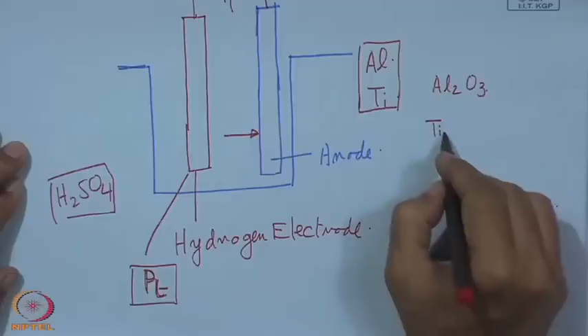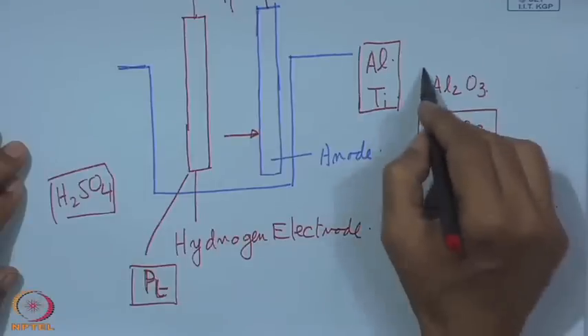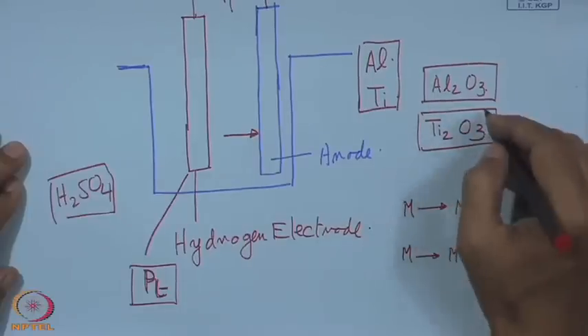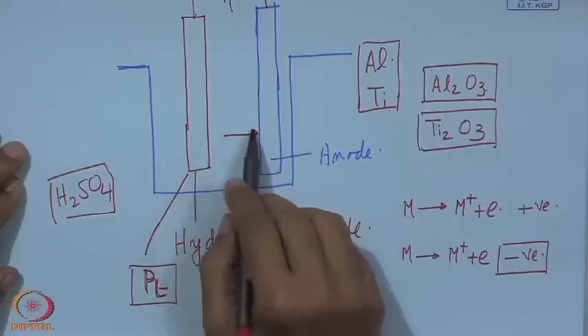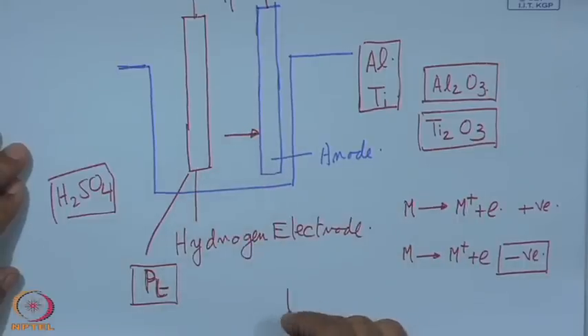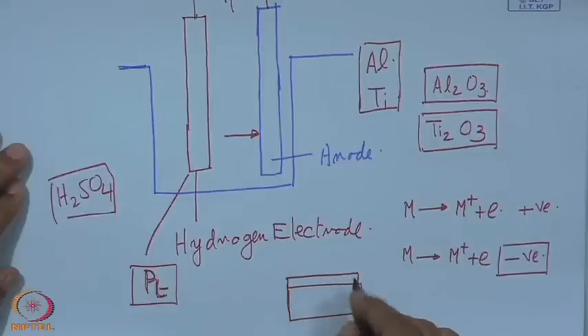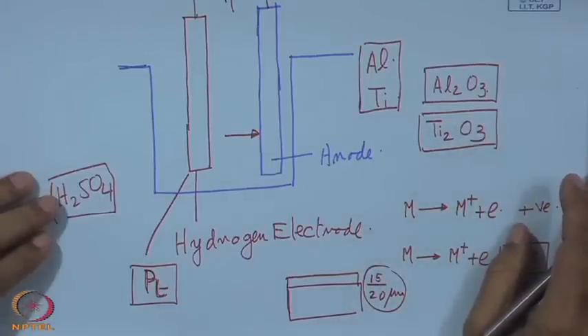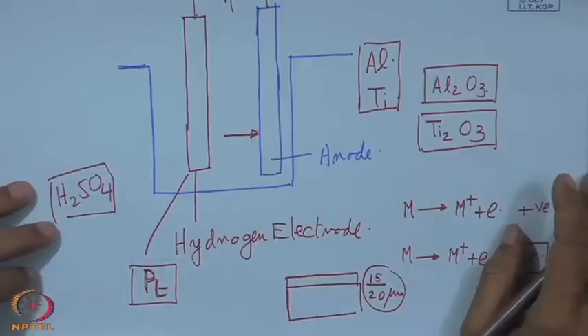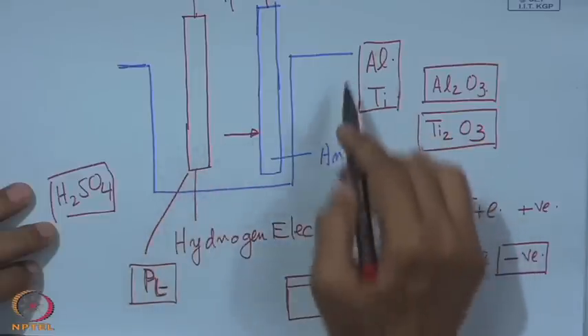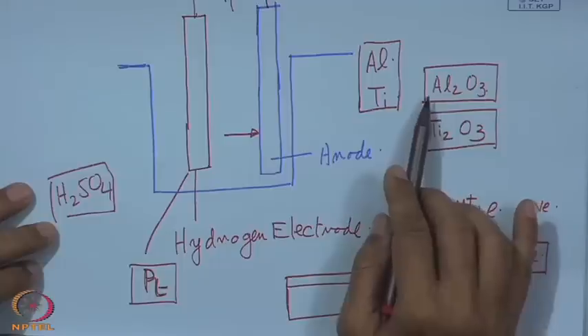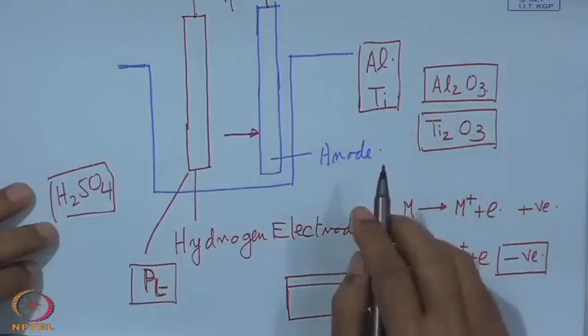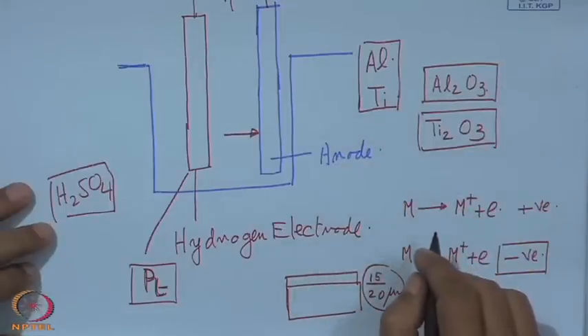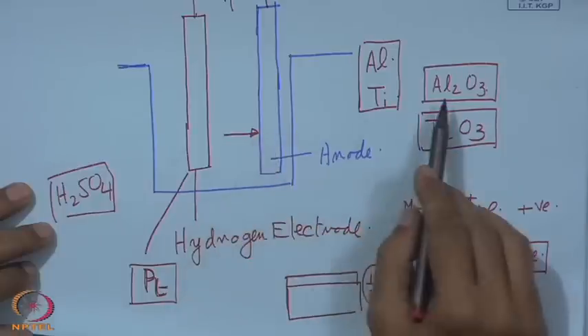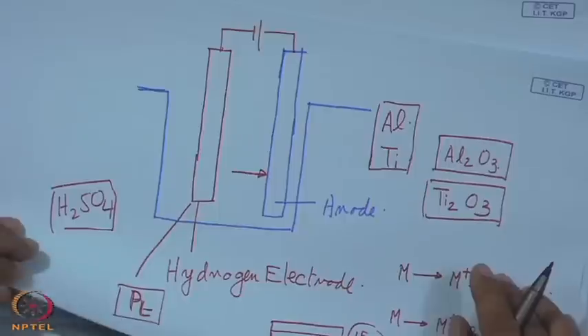It can also go with titanium with Ti2O3, but the interesting part of the whole thing is that this layer will immediately be a passive layer, and with this passivity no further reaction will occur on this side. So, we can very easily get a thickness of say 15 to 20 micron over the surface, and that will become this oxide of aluminium, and that is called the process of anodizing. And with some addition of dye in this solution, we can also have some coloration of this anodized film, and it can have blue, yellow, some kind of color according to the choice. So, basically it is forming one passive oxide layer by this anodic action, which makes the thing passive, it becomes a non-conductor of electricity.